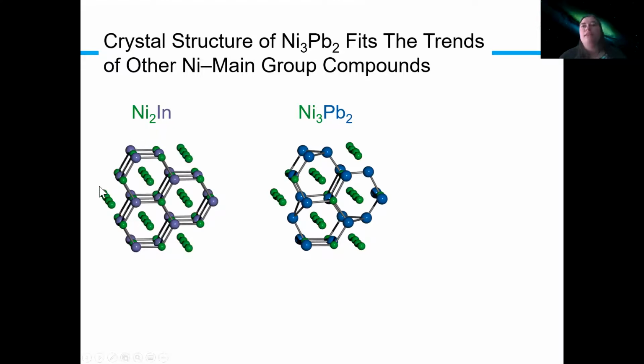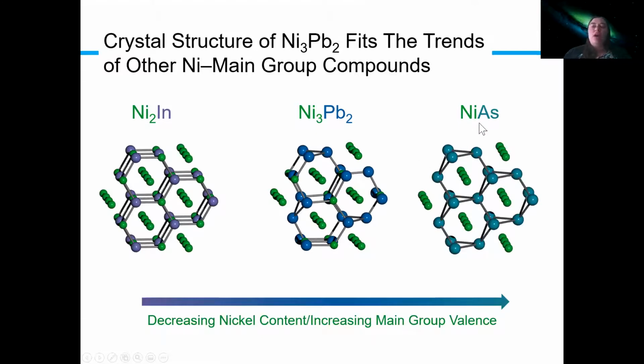Nickel 2 indium has these chains of nickel, and then alternate hexagonal nets with alternating nickel and the main group element. In the nickel 3 lead 2 structure, this nickel site is half occupied. So we have absent, absent, present, present, absent, present. Whereas in the nickel arsenic structure, that site is completely absent. There are no nickels present in